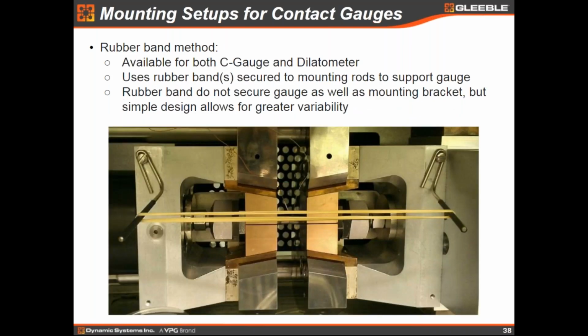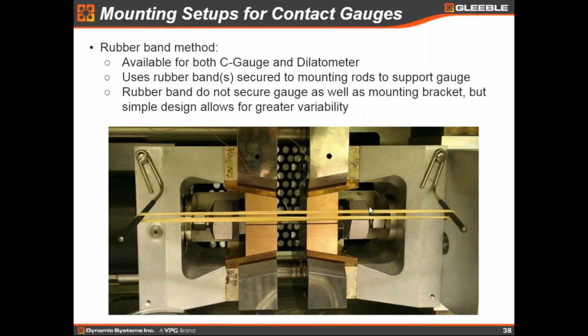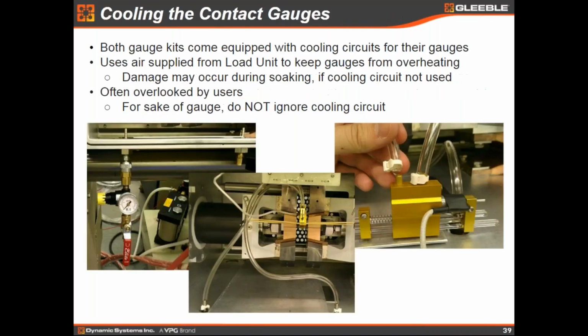The rubber bands, on the other hand, can be used with both the C gauge and dilatometer. Simple setup: just have these mounting rods right here and here, and rubber bands, one, two, however many you want, go between them, and then you stick your gauge right between there, right in the middle, and just try to secure it the best you can. Now the benefit of that is you can orient them however you want. You can do a lot of different things with that. But the gauge isn't as securely mounted, obviously. If you're taking it in and out a lot, there's potentially more variability in that. There's less of a guarantee that you're going to be measuring just an isothermal plane. You're not going to skew it across the sample a little bit. That can happen with this more easily than with the mounting bracket method.